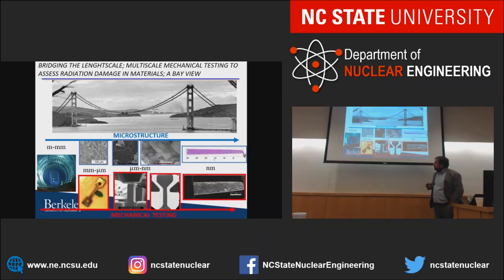And so the other nice thing you can do about small-scale mechanical testing is that if you make your mechanical test samples smaller, and here's a pillar and a tensile and a compression test, and obviously a tensile test at different length scales, you can test different microstructural features. So if your mechanical test is on the order of a grain boundary, you can figure out what is the strength of a grain boundary before and after radiation. You can test delta ferrite versus regular ferritic martensitic microstructural features in your ferritic martensitic material. Or you can test all kinds of different features you may be interested in and really bridge the length scale from reactor size to the atomic or nano size, if you will, and test whatever you're interested in. And so I want to show you these tests we're doing and developed over the years to flush out the differences between displacement damage and helium damage in the material.